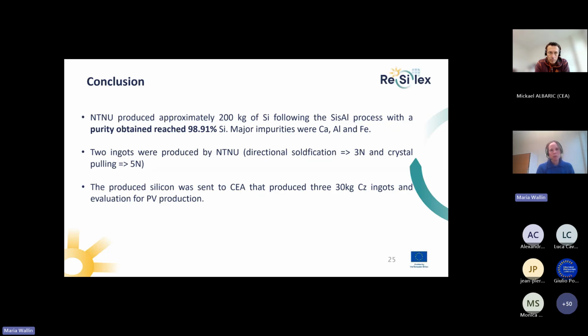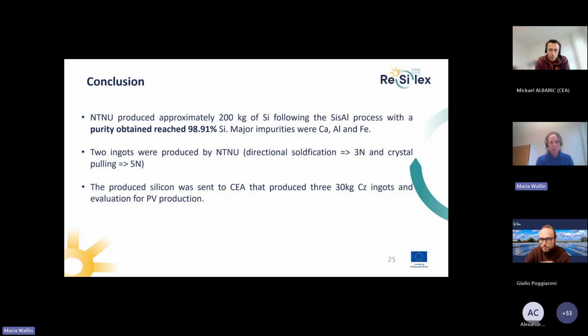And I said major impurities were calcium and aluminum. We also had some iron in that ingot, or in that metallurgical grade silicon. And from that, as I've shown you, we produced two types of ingots. One with directional solidification, where we only reached 3N, and also this crystal pulling, where we're able to reach 5N. And these ingots were all sent to CEA. So Mickael will now tell you what he did with the material that we produced. Thank you.